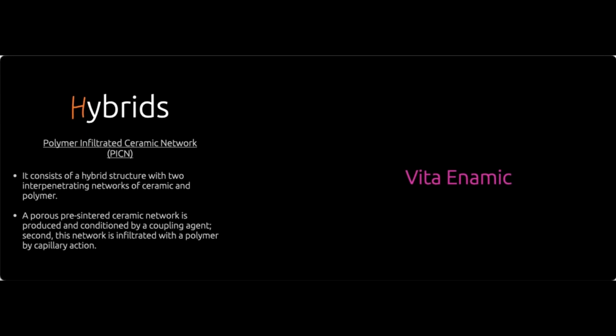The way you should think about Enamic, I think, is, you know, the sponge that you have in your kitchen to do your dishes, that blue or yellow sponge that you have? Well, that is your glass ceramic. It's full of pores. Now, when you put your detergent on it and it starts soaking into it, that will be the resin. So those two things together, after they cure the resin, are what Enamic is. And this is what I want to concentrate on a little bit, maybe a lot, because a lot of people have a lot of confusion about Enamic. They think it's a resin. No, it's not a resin, it's a glass ceramic.